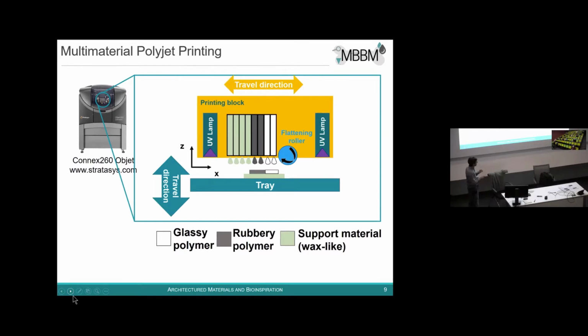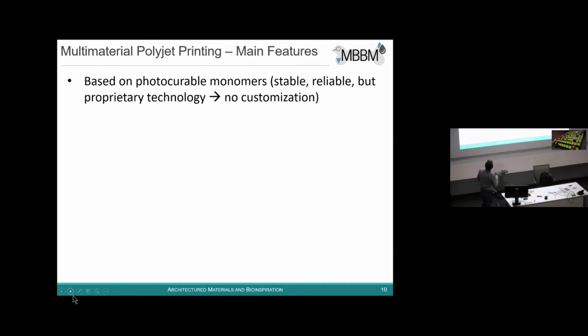And what is nice is that with this printer, you can combine different basic polymers, so liquid inks, which in this animation are only 2, but now the new printers work with up to 5 different inks. And different inks then result in cured polymers with very different mechanical properties. So this technology is called PolyJet printing, and is based on photocurable monomers. Since it is a commercial printer, it is stable and reliable, but of course it is a proprietary technology, so there is no possibility yet to customize the inks, for example, inserting nanoparticles and so on. This is something which is not really easy to do.